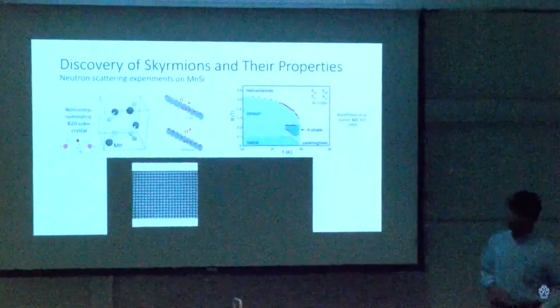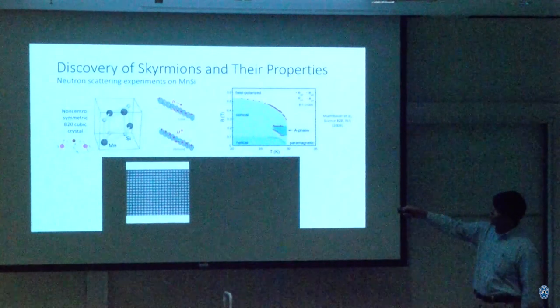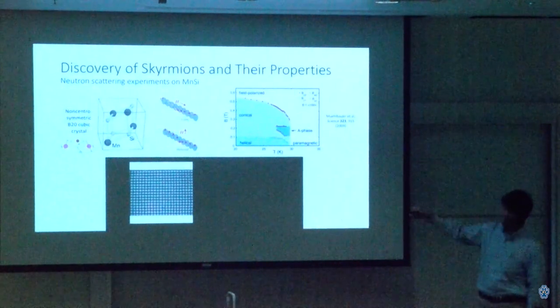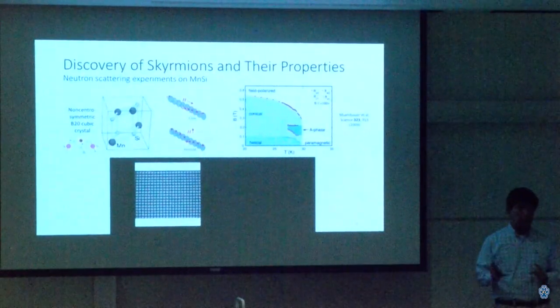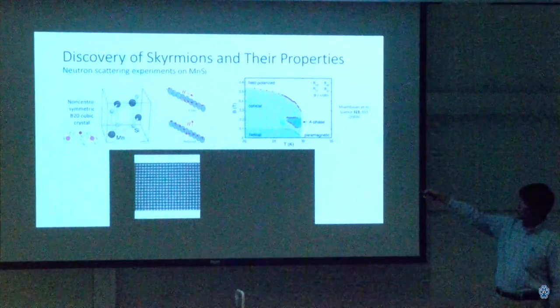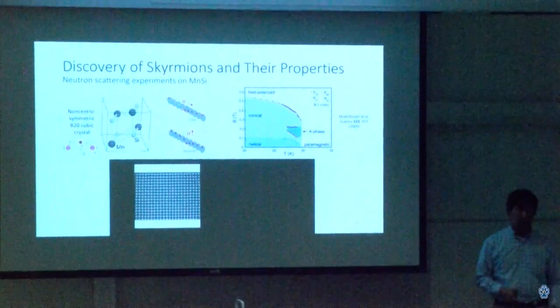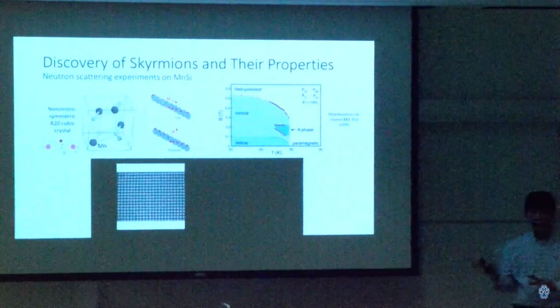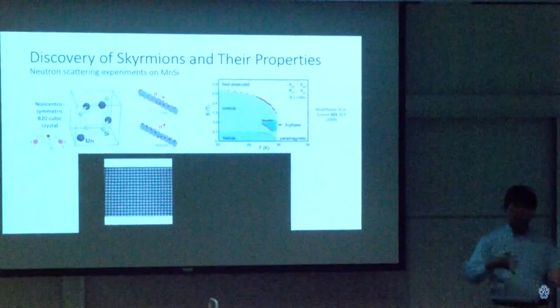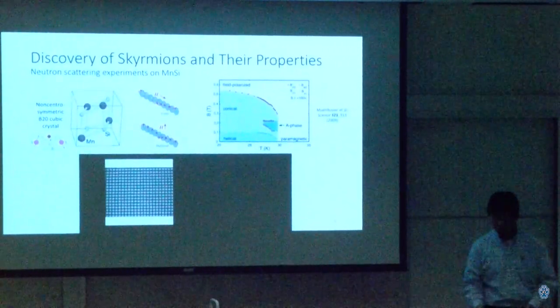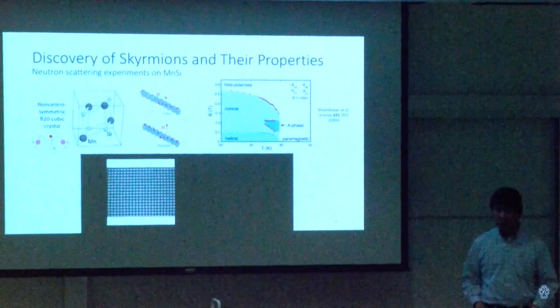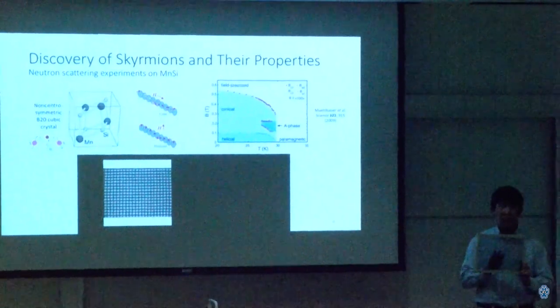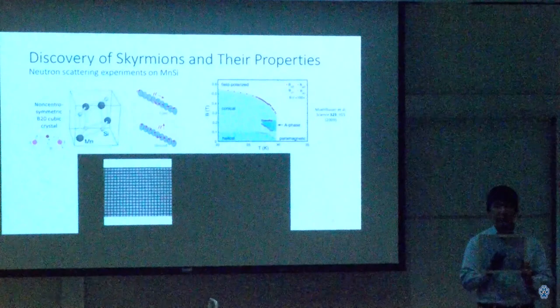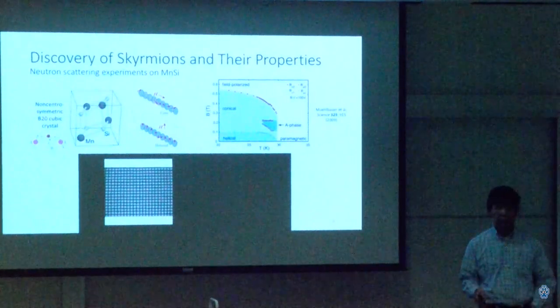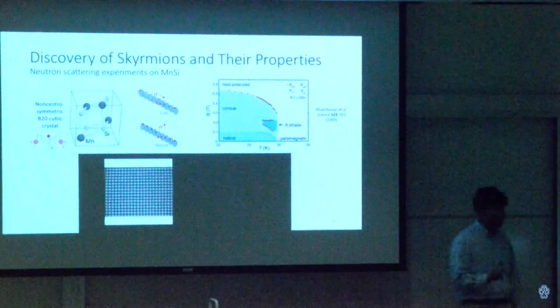If the magnetic texture in manganese silicide does something different from that of a helicoid or a cone, like they suspected would happen in the A phase, then whatever diffraction pattern they get from this beam of neutrons will change. So if the diffraction pattern through this suddenly changed on you after I say blue on it, you would suspect that something happened to the structure.